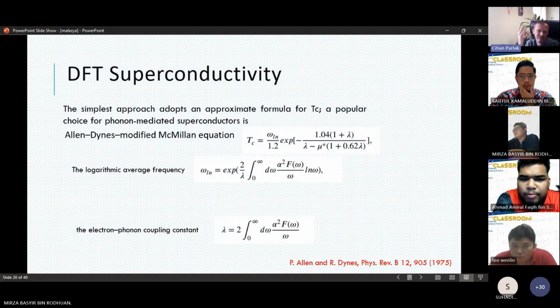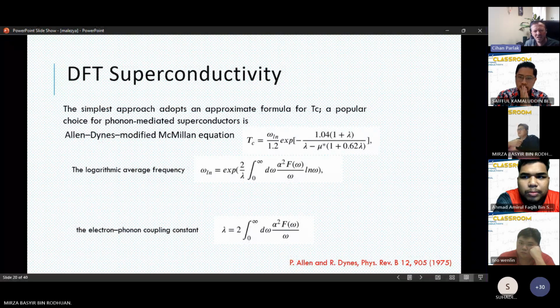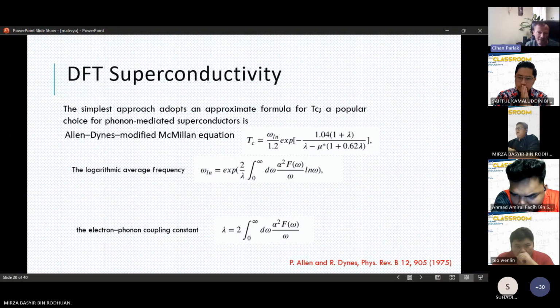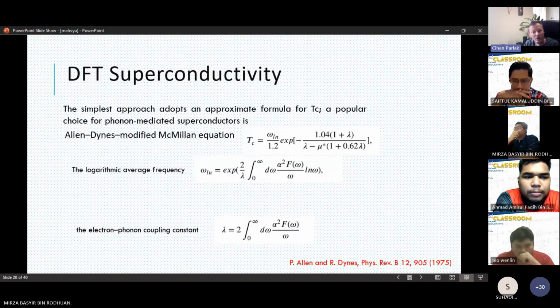The two main things we talk about in DFT superconductivity: one of them is the electron-phonon coupling constant. It comes from the BCS theory, the old theoretical explanation of type 1 superconductors, and it has a very strong effect on the critical temperature. Most of the codes and very popular calculations use the Allen-Dynes modified McMillan equation. If we can calculate the phonon frequencies, we can calculate the logarithmic average of the frequency and the electron-phonon coupling constant, and then we can get the Tc value of a superconductor with the aid of density functional theory.